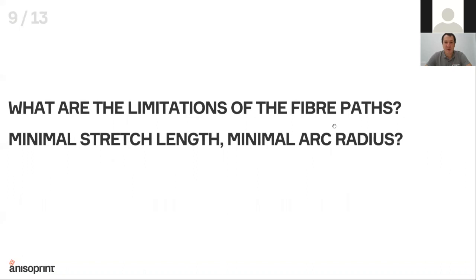What are the limitations of the fiber path? Minimum stretch length, minimum arc radius. Yeah, I've already answered a little bit about the arc radius. So the turn-in radius is about 1 millimeter, and the minimum reinforcing radius is about 8 millimeters. The minimum stretch length depends actually on the cutting capabilities. So the distance between the cutter and the nozzle tip is 45 millimeters. So this is the minimum fiber length that you can print.